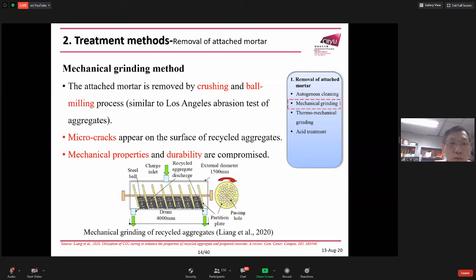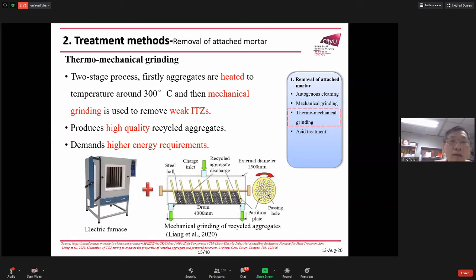We may also modify this method by thermal heat treatment. So this comes the third method, which is thermomechanical grinding. There are two stages. First, the aggregates are heated to a temperature of 300 Celsius and then mechanically ground to remove the weak ITZs. It produces high quality recycled aggregate, but the problem is that it demands high energy because it needs heat treatment before grinding.